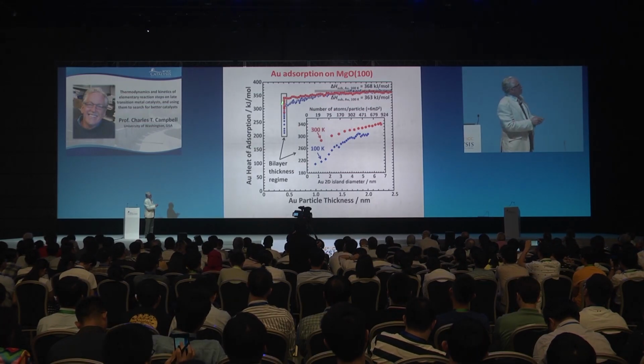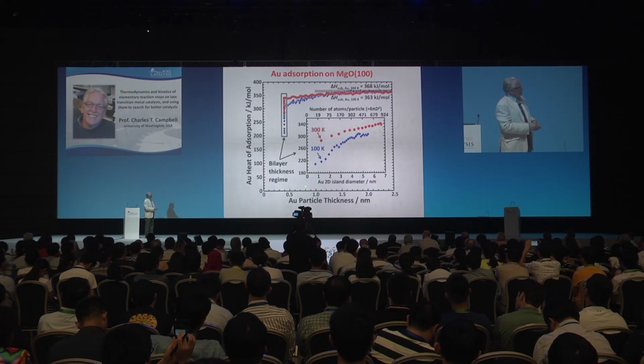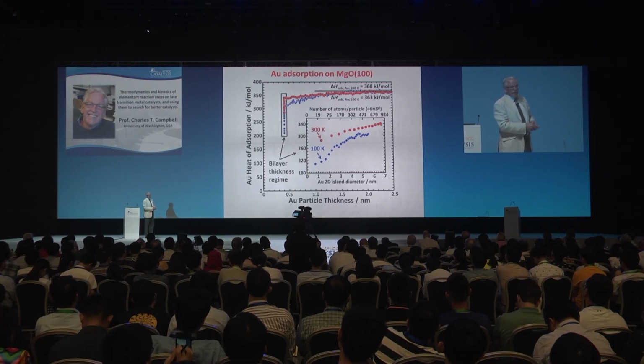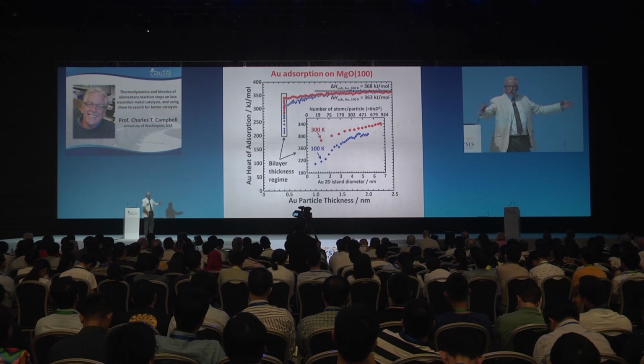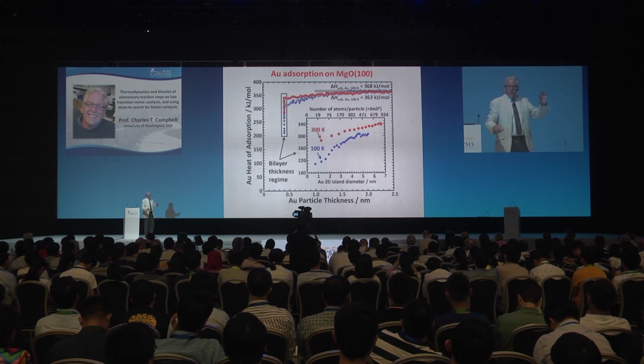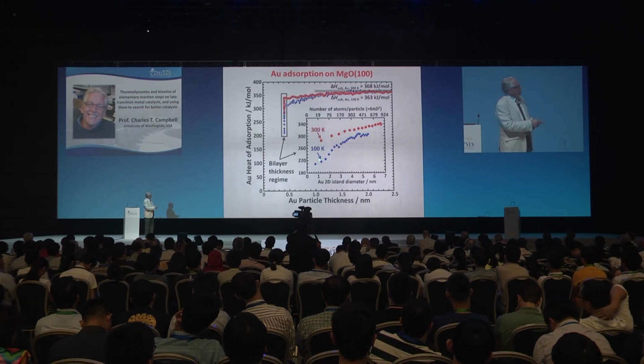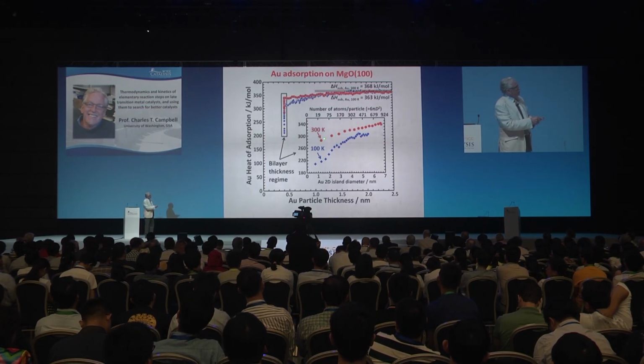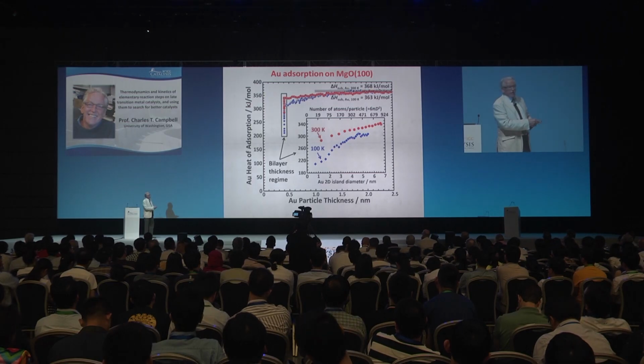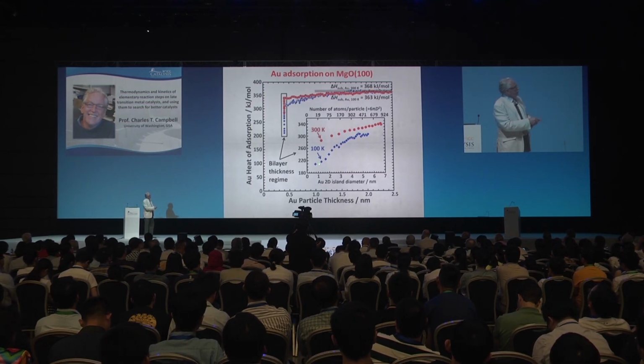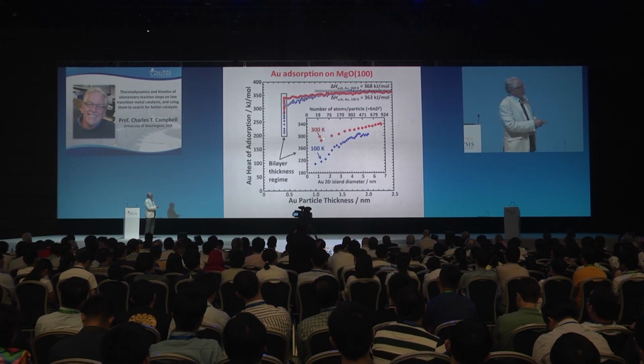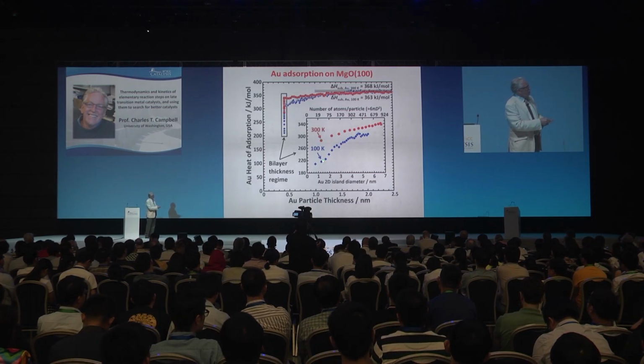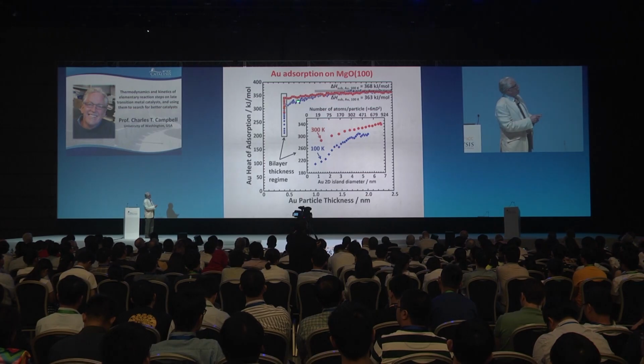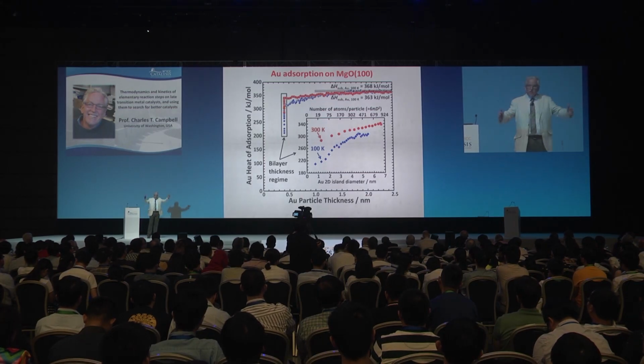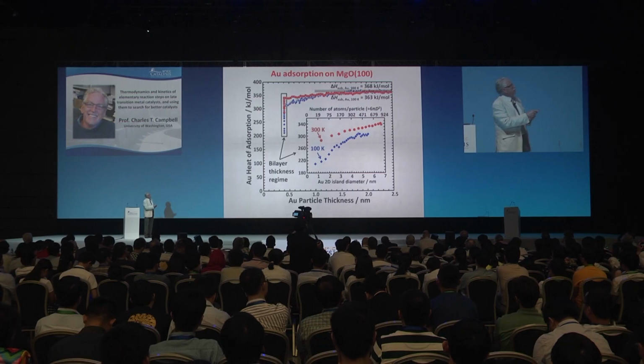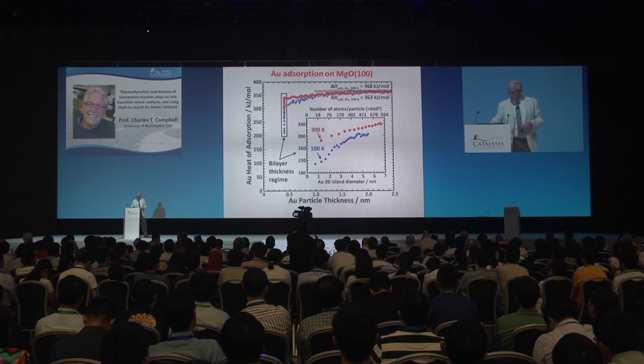And so there's 2 regimes. In this regime, we can plot the heat of adsorption essentially as a function of the average 2-dimensional island size for islands that are always 2 atoms thick. You can see there's quite a difference between 100 and 300 Kelvin because these are at step edges and these are on terrace sites. So that emphasizes the difference between clusters on defects and not on defects. In this size regime, basically the islands are 7 nanometers in diameter and they're just getting thicker, and you see an effect as well there.